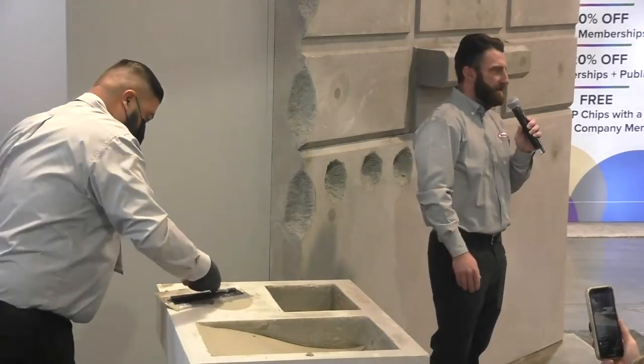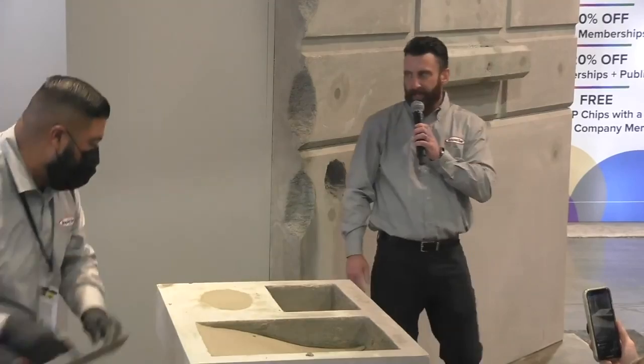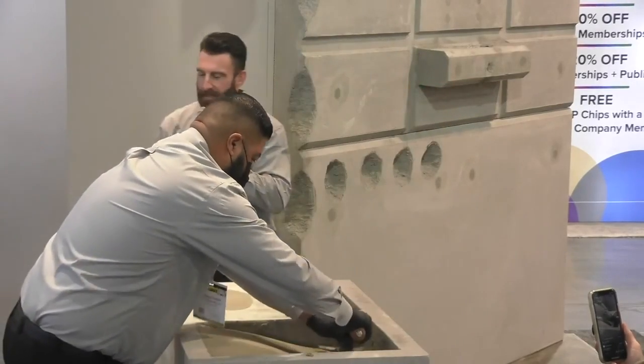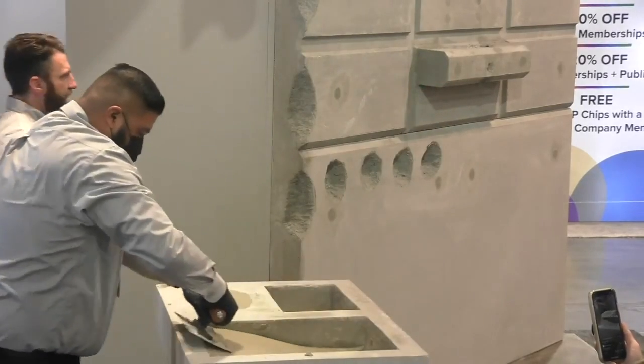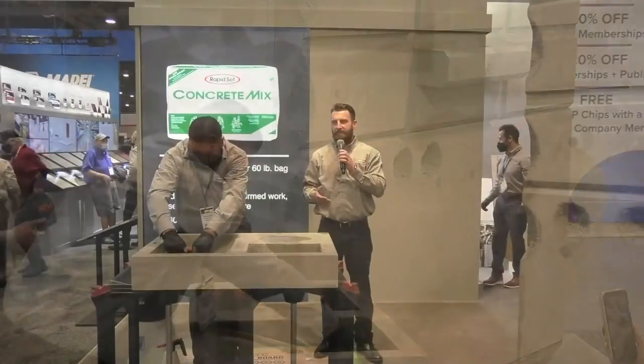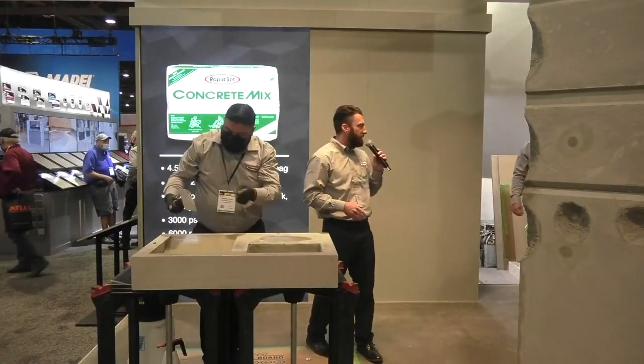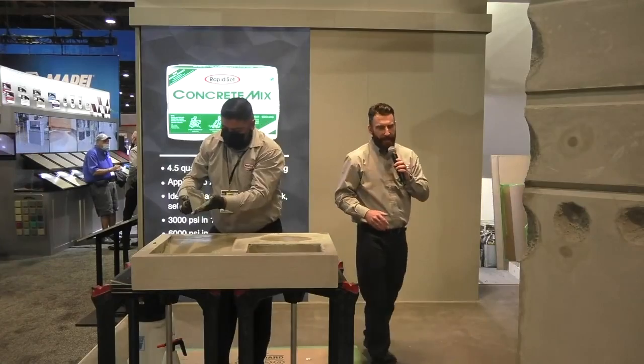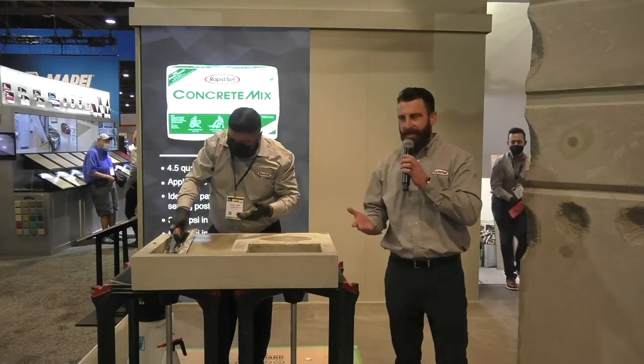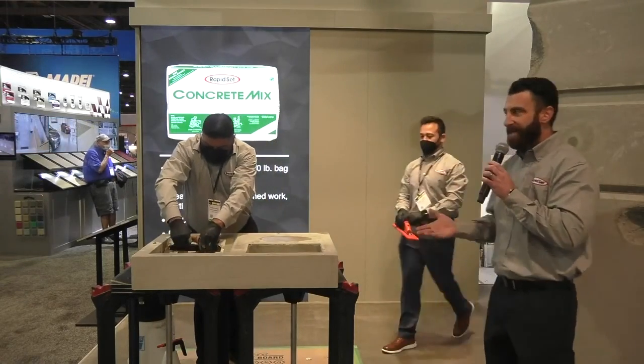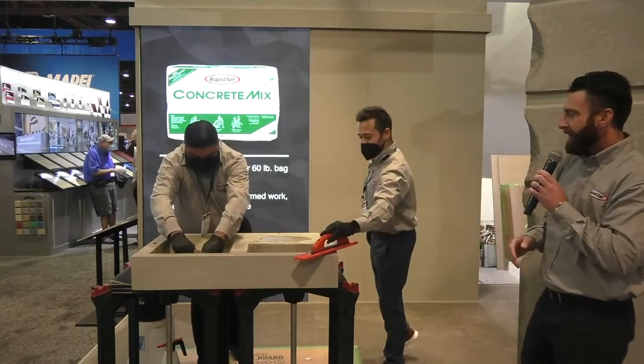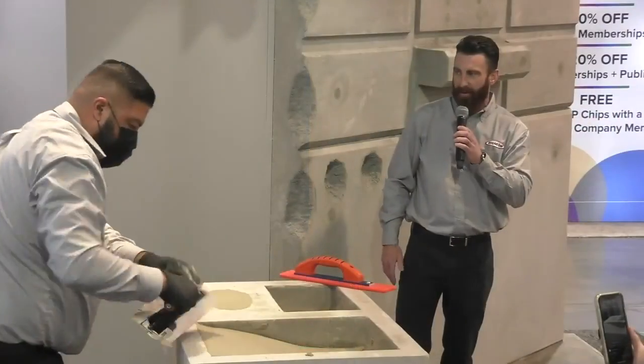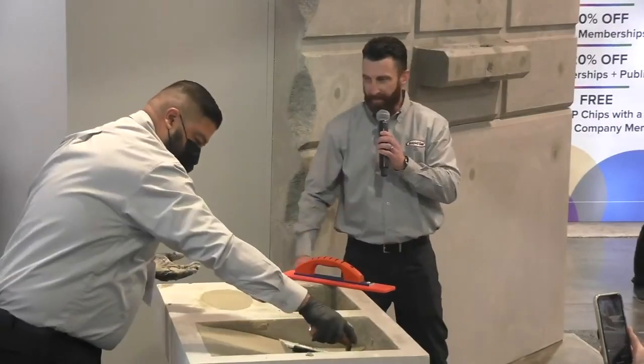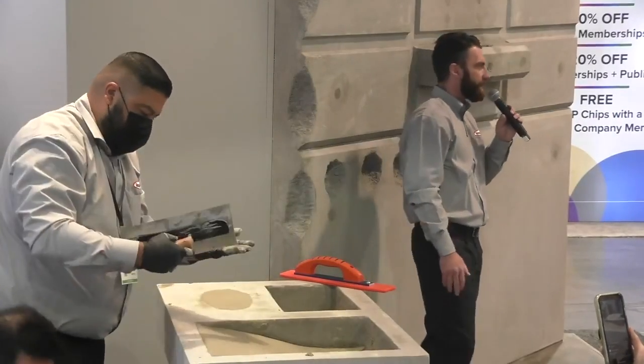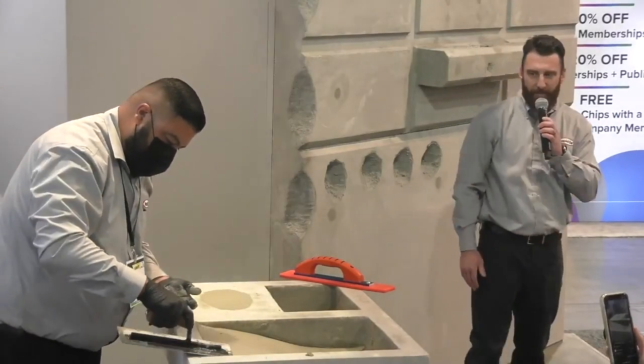So next we'll be moving on to the concrete mix. The concrete mix is designed with 3/8 inch aggregate, so it's great for repairs from 2 inches all the way up to 24 inches thick. It's also based on the Rapid Set Cement technology, so it's very fast, about 15 minutes of working time, and will gain structural strength in 1 hour. I don't know if you can see down on the bottom, it's 3,000 PSI in 1 hour and 6,000 PSI in 28 days.